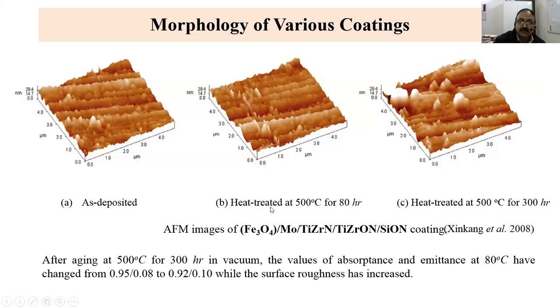This is heat treated at 500 degrees centigrade for 80 hours. And this is heat treated at 500 degrees centigrade for 300 hours. So after aging at 500 degrees centigrade for 300 hours in vacuum, the values of absorptance and emittance at 80 degrees centigrade have changed from 0.95 to 0.92, and for emittance it is 0.08 to 0.10, while the surface roughness has increased. You see that the surface roughness has increased when we are undergoing the heat treatment.